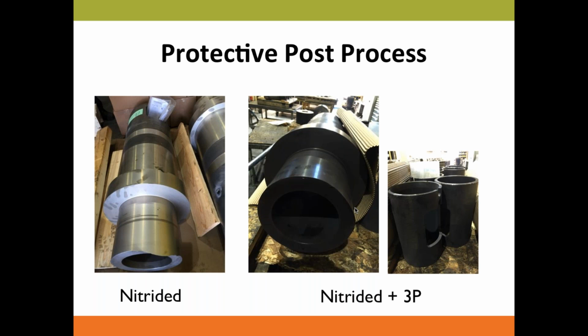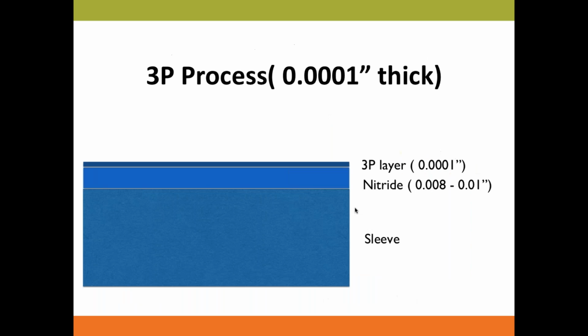So now we talk about wear of the nitride, but nitride itself is not a good corrosion layer against molten aluminum. So what Castle is doing right now is, after you nitride, we put a protective layer on top. This protective layer is very thin. It's less than 1/10 of a thou, so it will not change the dimension at all. And it's on top of nitride.